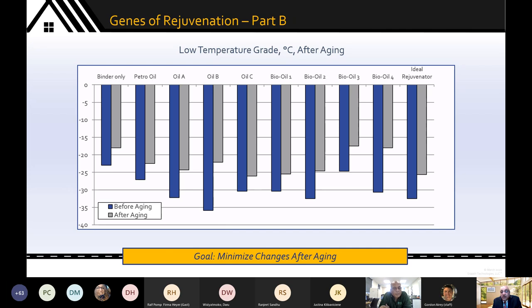So what you're looking to do as we created our rejuvenator was not only to preserve a high level of performance, this is about dosage efficiency, but also to reduce the delta, reduce the change. And this is really how we came up with our rejuvenator. And this is just maybe one technique that you may want to consider for looking at this material.